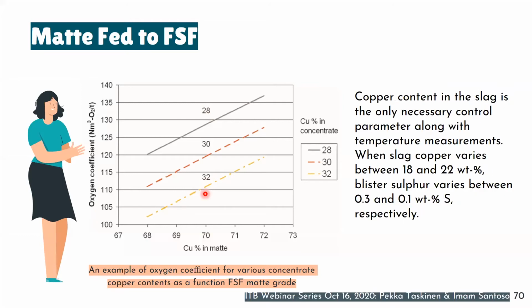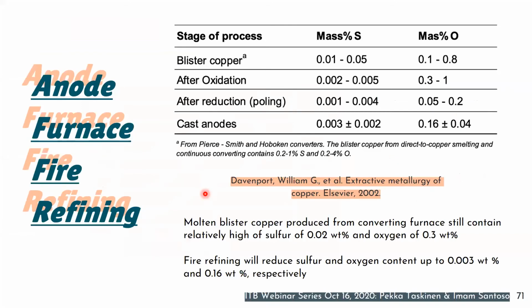So now the converting process produces blister copper, but the blister copper itself, we can see here, still has a very high content of sulfur. It is around 0.01 until 0.05 in terms of sulfur, and the oxygen can be 0.1 until 0.8%. The sulfur and oxygen are still very high.